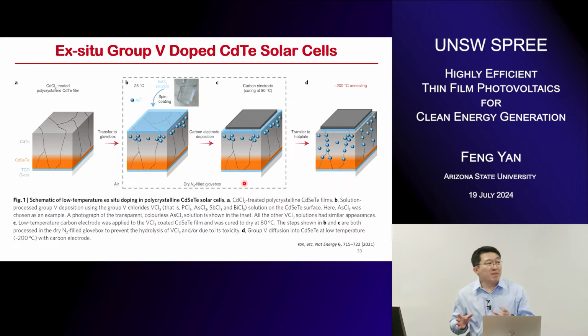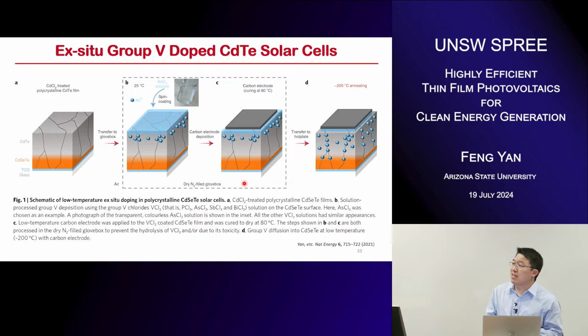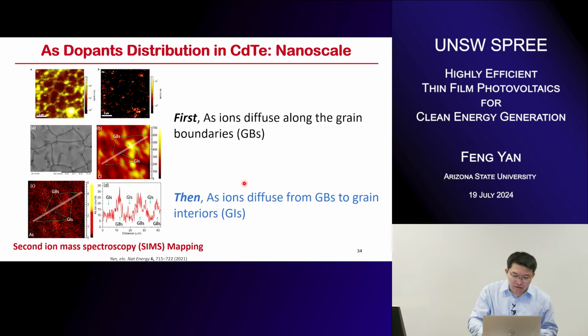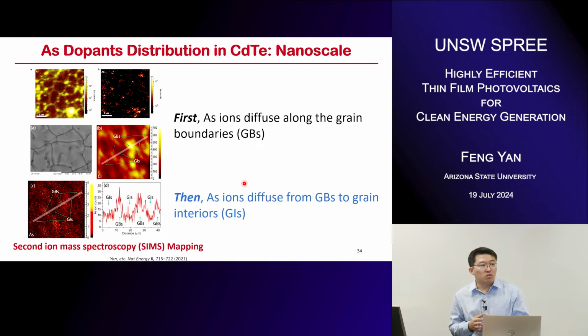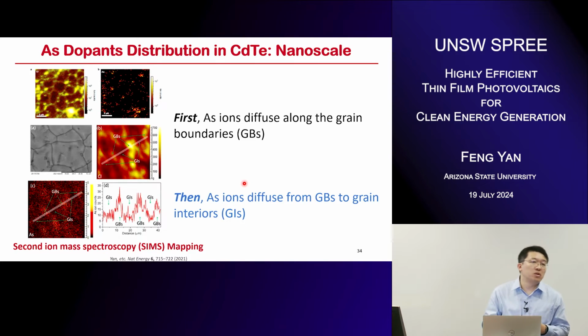Because of the time limit, I may not introduce the cadmium chloride treatment process. But what is pretty interesting is that this realizes a low temperature diffusion of the arsenic ions into the polycrystalline cadmium telluride. And the result surprised us initially, why it works. If we revisit the chemical distribution inside this polycrystalline, we find similar behavior to the copper ion doping. The arsenic ions can initially drive into the grain boundary and then use extra thermal treatment to drive into the grain interior,